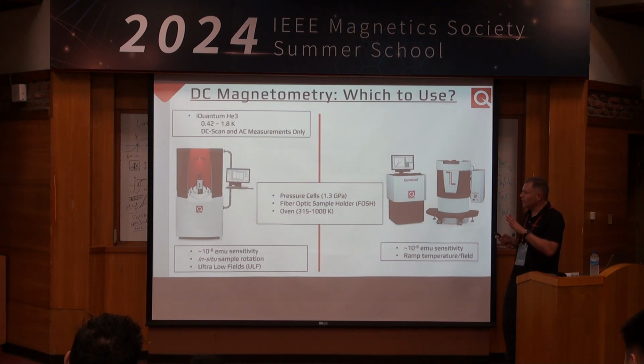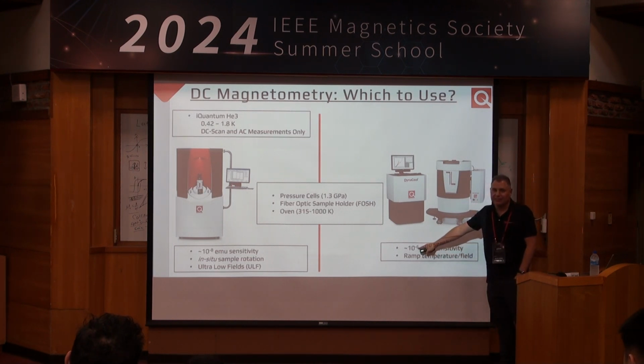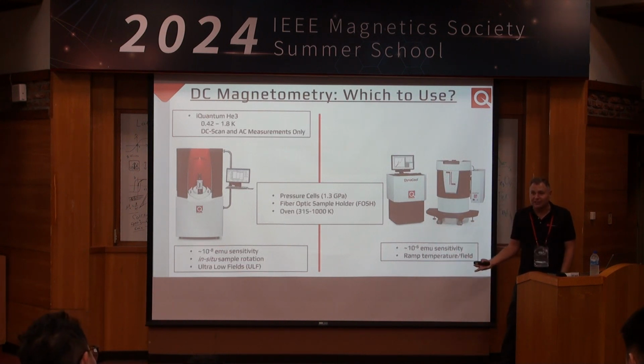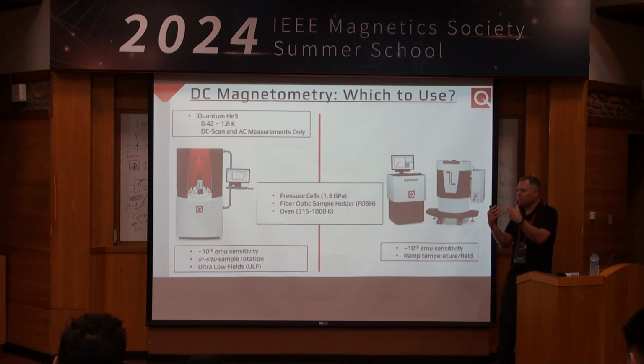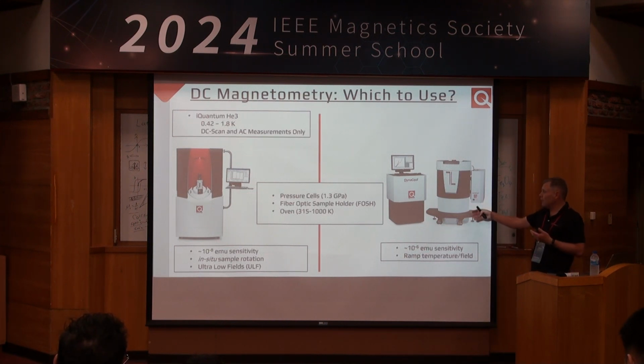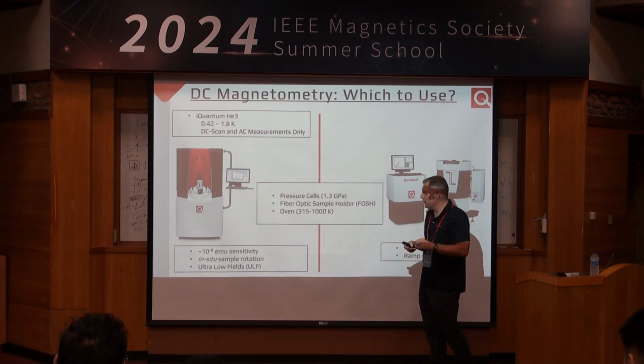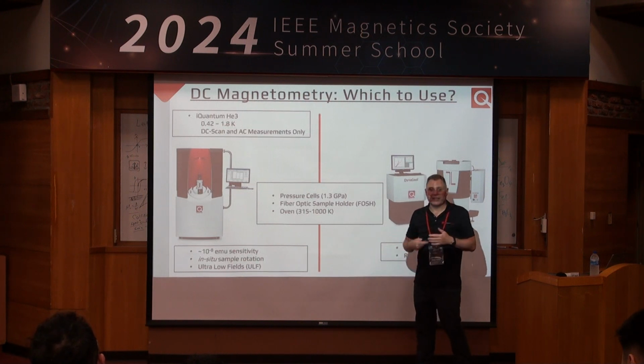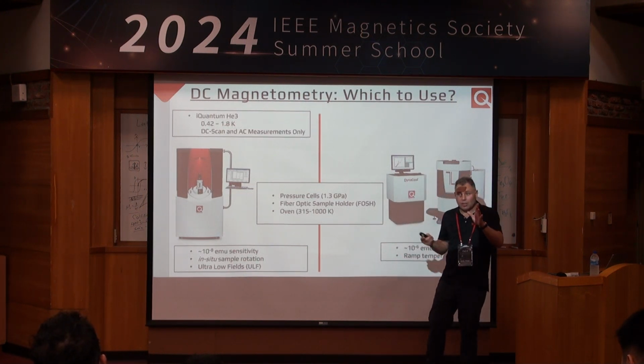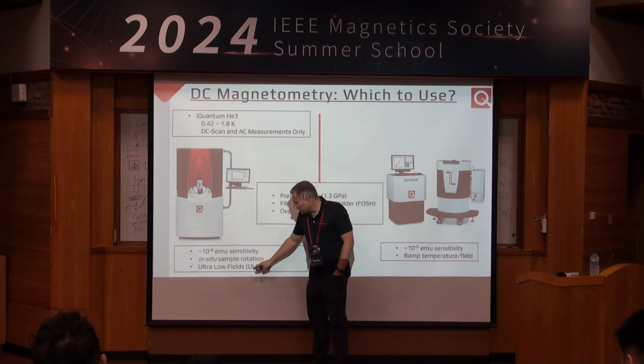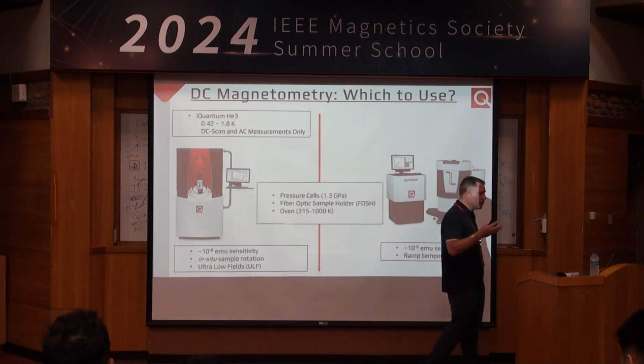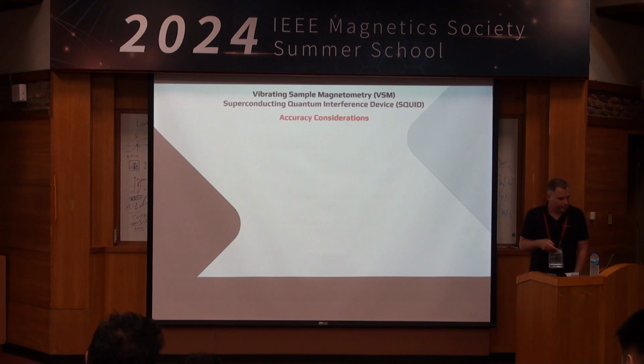So the moral of the story is you've got to buy both, right? If you want to do everything. That's the moral of the story. Joking aside, really it comes down to the sensitivity. If you've got samples with milli-emu sensitivity, you're dealing with chunks of nanoparticles, large milligram sort of volumes, you might get away with this. You're probably going to measure faster here. If you're dealing with ultra-thin films, those things that are less than a nanometer thick, you might want to use a system like this. It all depends on your sample. If you have very low coercivity samples, this option here is going to be what you're going to want. So again, it all comes down to what your sample is.